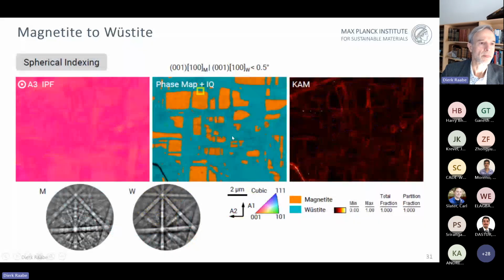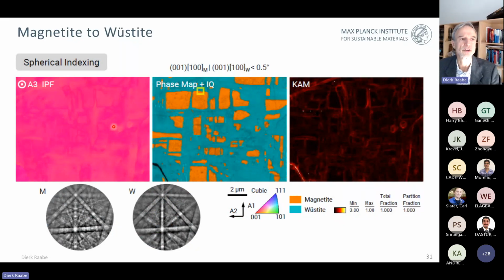Here you see a single crystalline area, where on the left-hand side, everything has more or less the same color in the inverse pole figure. We look at a single crystalline portion of a magnetite to wüstite, and you see the two phases, the orange colored magnetite here in the center and the wüstite surrounding it. And you see this blocky structure where there is kind of an isostructural transformation between the two, as I've mentioned before. And in the kernel average, you see that you also measure for the local curvature or accumulation of geometrically necessary dislocations.